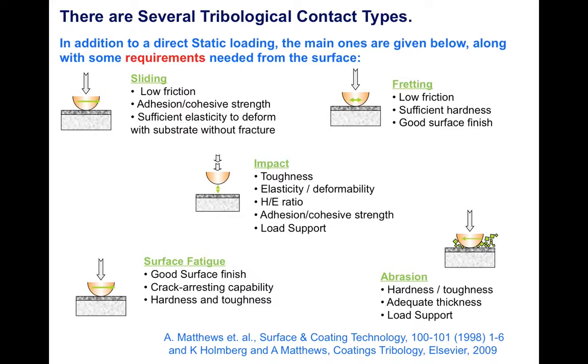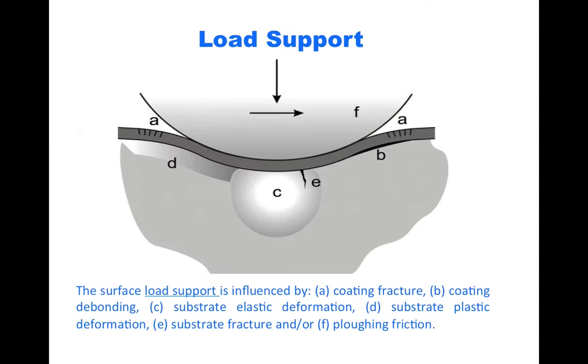Another thing we talk about is the load support. So it's the support that the underlying substrate gives to the coating. And again, people talk about load support, but they don't define what they mean. I mean, we all realize load support's important, but what do we really mean? Well, a lack of load support can make things fail in different ways. If you don't have adequate load support under the coating, the coating could fracture, the coating could debond, the substrate could elastically deform, which could take the component out of tolerance. The substrate could plastically deform, so it could take it out of tolerance permanently. And the substrate could fracture, or you could get plowing friction due to the increase in deformation.